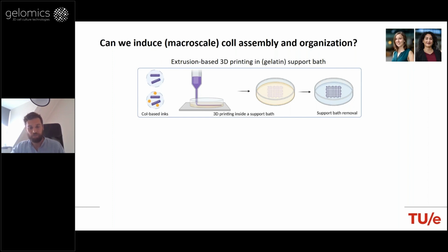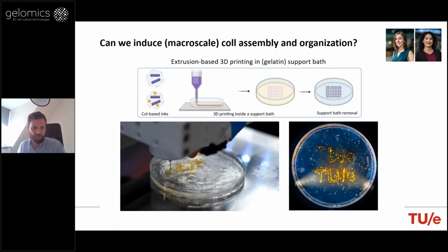We combined it with or without the crowding agent, and then we extruded this in a support bath composed of gelatin at neutral pH. And then this shift between an acidic ink in contact with the gelatin bath at neutral pH led to inducing the fibrillogenesis and self-assembly of collagen. And then this gelatin, as most of you know, can be removed by just increasing the temperature, so basically melting the gelatin.